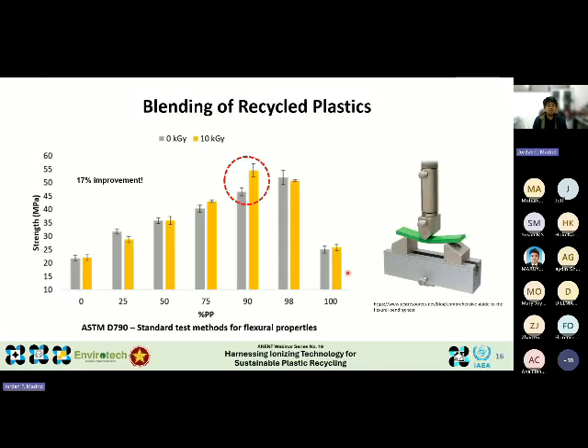So after characterizing them, we then used them for extrusion, molding, and then mechanical testing. Just like in any recycling project, the goal of the team is to maximize the utilization of plastic waste. To pursue this, we explored the possibility of blending our feedstock, polypropylene and high-density polyethylene, at different ratios. For this stage, we chose flexural strength as our initial response parameter because, as I've mentioned earlier, one of our long-term goals is to develop materials for housing and construction, and in this field, bending resistance is an important property.